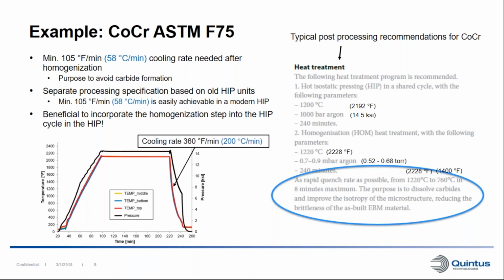And here's an example of a high pressure heat treatment. So this is for a cobalt chrome material, ASTM F75. And if we look on the right here, we have a specification found in literature for the post-processing of this material. So as we can see, as a first step, we have a HIP cycle specified, 1200 degrees Celsius and 4 hour soak time. And after the HIP cycle, we have another homogenization step, which is performed in vacuum.